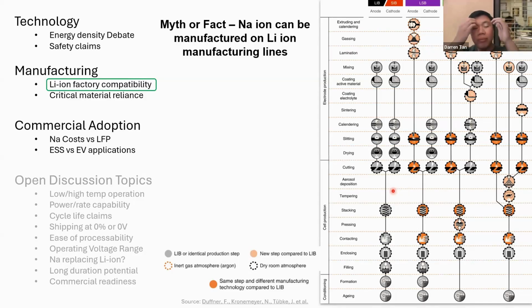For the same 10 gigawatt hour factory that produces lithium-ion batteries, if your energy density of the sodium-ion battery is half of lithium-ion, I'm talking about volumetric energy density, because production is done by volume, right? You do it by units, not by weight. That means that your 10 gigawatt hour factory becomes a 5 gigawatt hour sodium-ion battery factory, right? And it's the concept of throughput. So that means your OPEX cost per unit doubles.